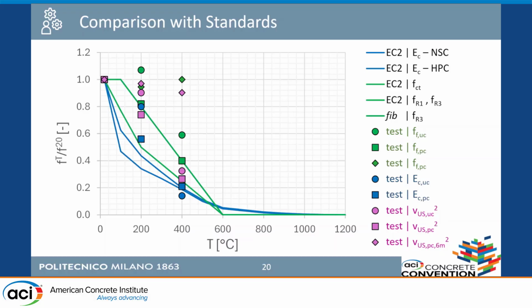The magenta rhombus represent the measurement of ultrasonic pulse velocity after 6 months. So we can see that also regarding stiffness, even though it's not strictly stiffness, but is an index of stiffness, we have a recovery. So I think that, taking in mind what is the difference between hot condition and residual condition, we can see that we have some positive indications of what happened after the cooling. As I said before, if we go beyond 450 degrees C, the story totally changes.